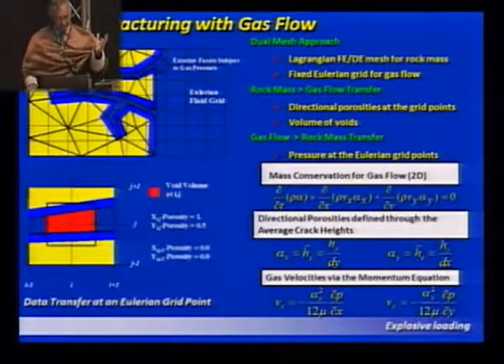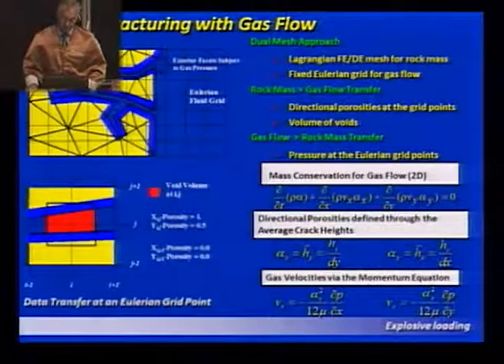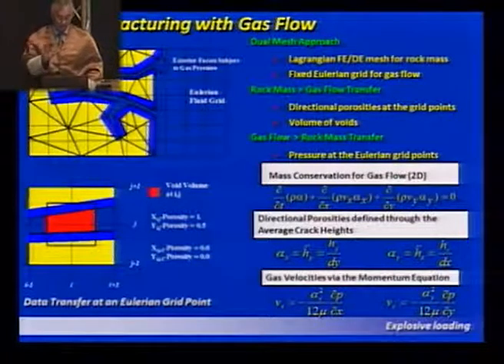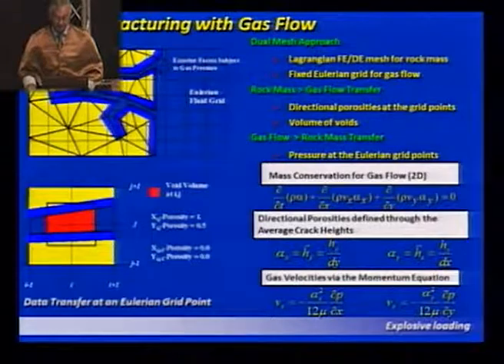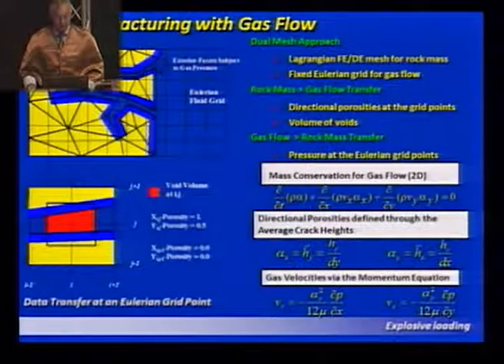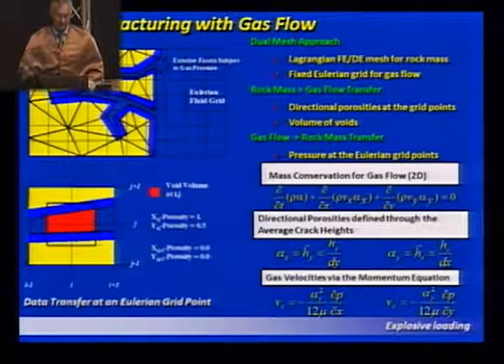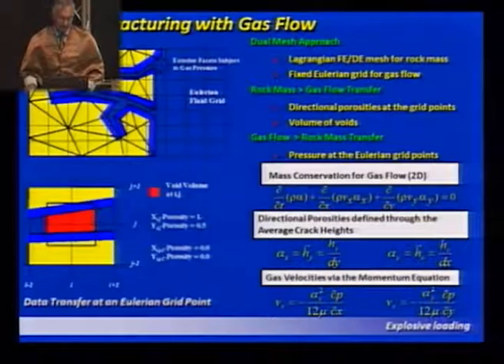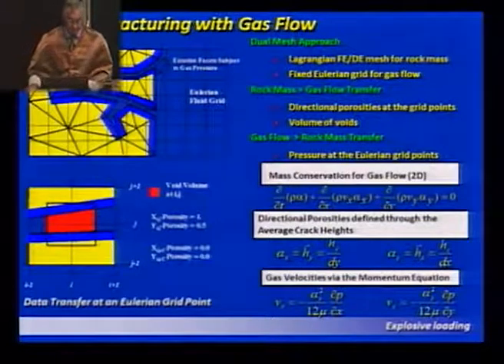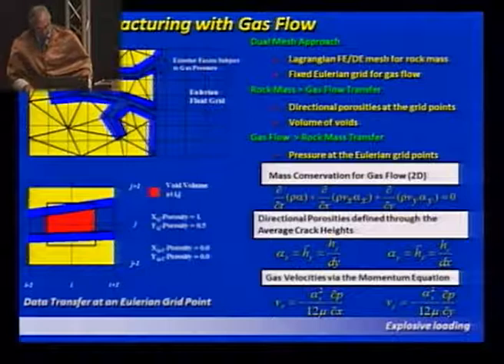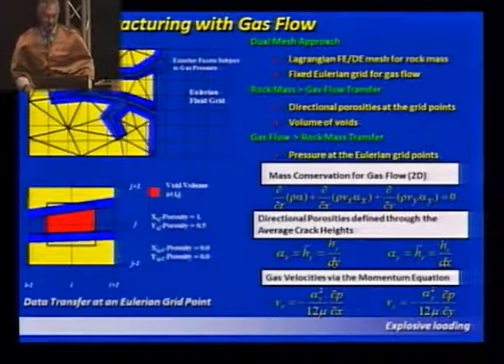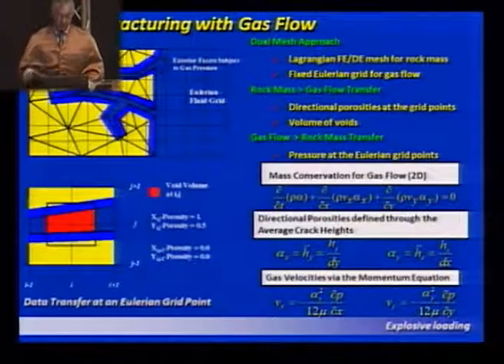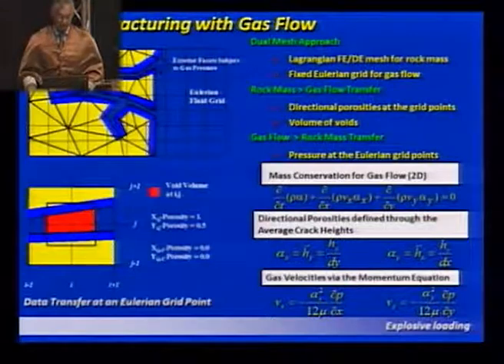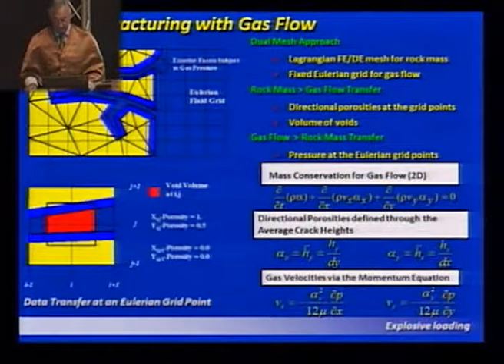We have the fracturing material, which we treat as a Lagrangian mesh, and then we have a background mesh on top of that, which is a fixed mesh. It's a Eulerian grid, and we've got to solve the gas equations on the Eulerian grid. And we pass information between the two grids. From the rock fracture model we obtain the porosities in the rock, which we then use in the gas flow model to determine the pressures.